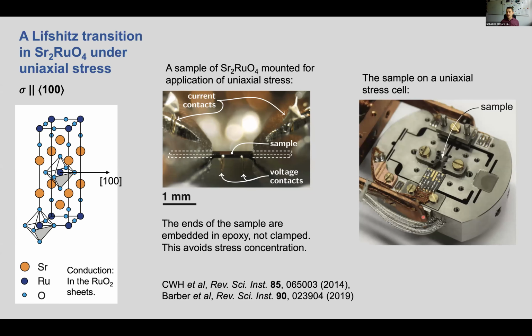And here's a picture of a sample mounted on a stress cell. This cell is almost 50 millimeters in diameter. It has piezoelectric actuators which drive motion of this block of titanium here. If we move this to the right, that compresses the sample, and then the force from the sample is applied to this block, and these titanium bars here and here, there are 4 in total, those bend slightly, and there's a capacitive sensor behind it that measures how much. In effect, that operates as a force sensor, so we can measure the force that is applied to this sample.